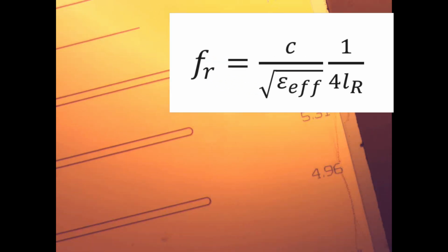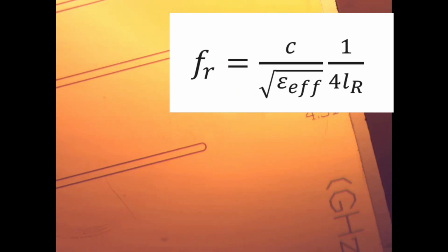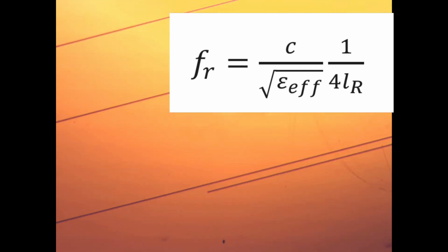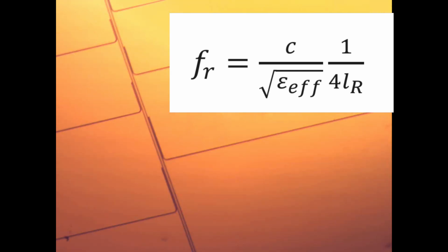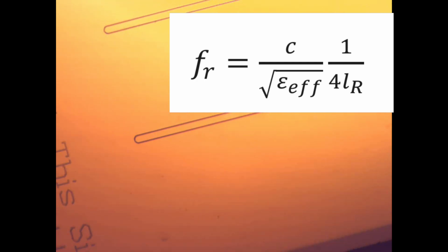Now sometimes CPWs are constructed with multiple resonators coupled to the same transmission line. We call them multiplexed. What you see here is a niobium on silicon CPW with quarter wave resonators multiplexed to the same transmission line. Each of these resonators has a different length, giving a different resonant frequency, or standing wave that forms in that cavity. The resonant frequency depends not only on the length of that cavity, but also how fast light travels by that cavity, as given by this equation.